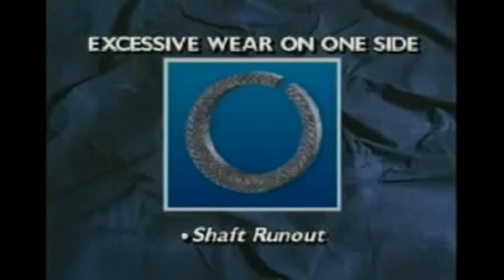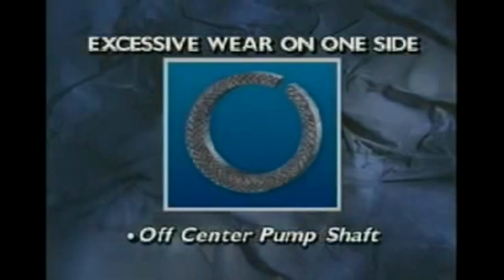Extrusion of the packing material could be an indication that the gland follower or stuffing box clearances are a problem, or that the packing material lacks the integrity to withstand the system service conditions. Packing rings that have excessive wear on one side may be caused by shaft runout or an off-center pump shaft.